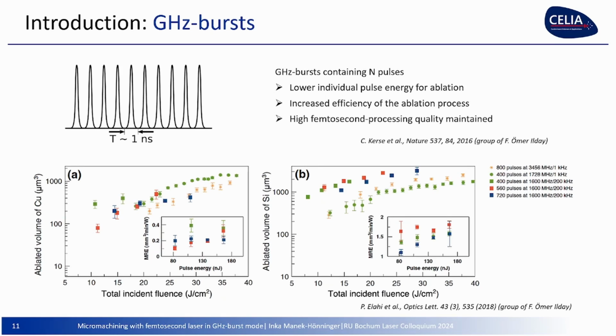He observed an increased efficiency of the ablation process, very nicely illustrated here. Very high ablation rates were obtained. This one is copper, and this one is silicon, so on a metal and on a semiconductor, he could show the ablation rates, given in cubic micrometers, or you can measure it in cubic millimeters per minute per watt.